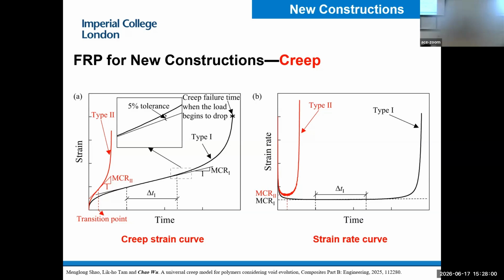However, in a cable-stayed bridge, the stress always changes in the structure. When you have a very heavy truck running on the bridge, greater than your design stress, it will fail much earlier, which is very dangerous. So we propose that the failure time should be defined at the end of the second stage, and we gave it some tolerance here. Unfortunately, we don't have any model that can predict the time there, the end of the second stage.